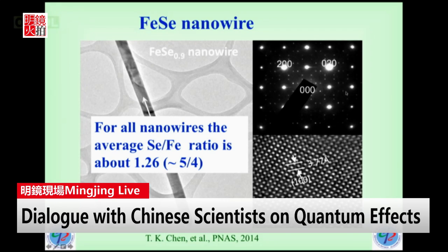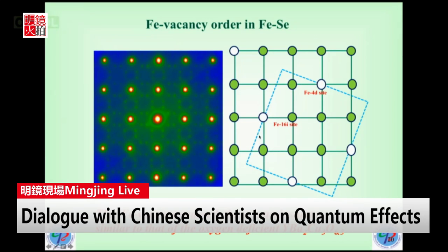So we were able to use some very simple analysis to try to pin down why the diffraction shows, in addition to those bright spots, some beautiful small spots. What are they? Okay, and the analysis tells us, if I look at the plane the iron sits on, every 4 irons, there's one missing. It goes periodically, okay? This is only one cell, but as you can see, it's periodic. So this kind of iron vacancy becomes a very ordered state in this particular 4:5 composition, which means we have two different iron sites. One is occupied, we call it the 16i site, and another is called the 4d site, which is empty.